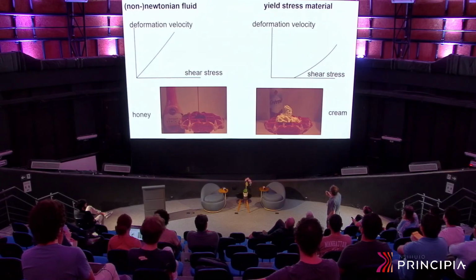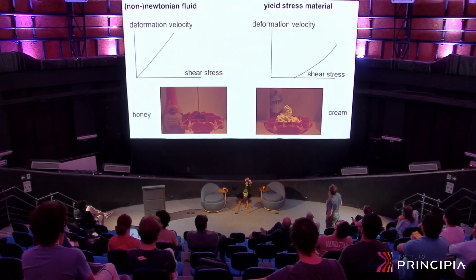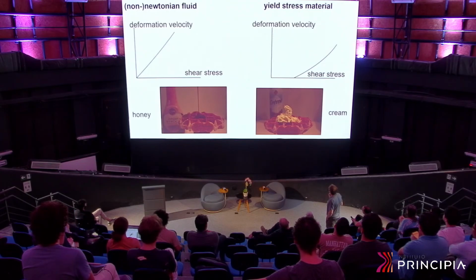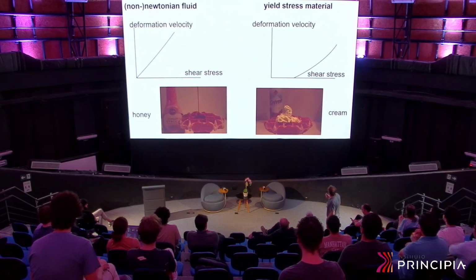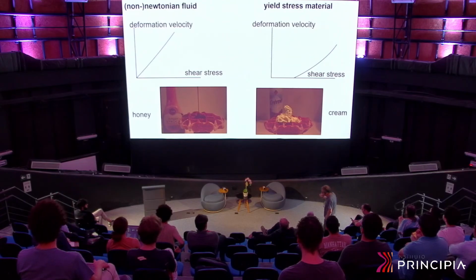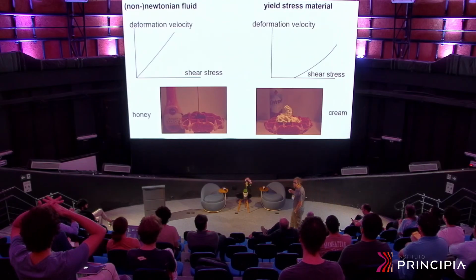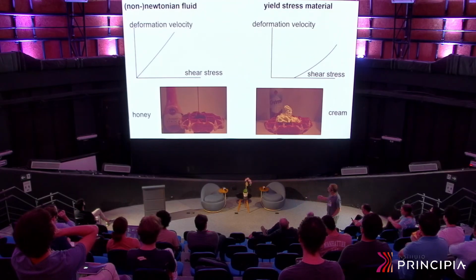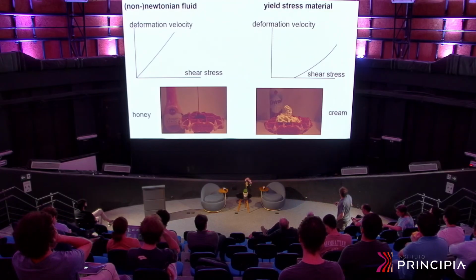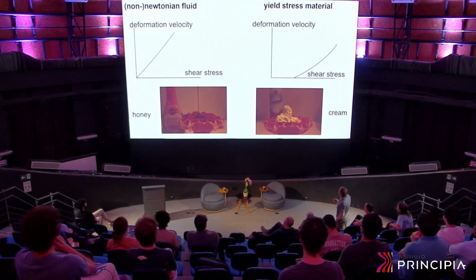And this indicates that the deformation velocity as a function of the stress in this kind of material has a critical yield stress here. If the applied stress is lower than this critical value, the material behaves essentially like a solid, and if you apply a stress that is larger than that value, it essentially behaves like a kind of liquid, okay? And there are many materials that behave in this way.